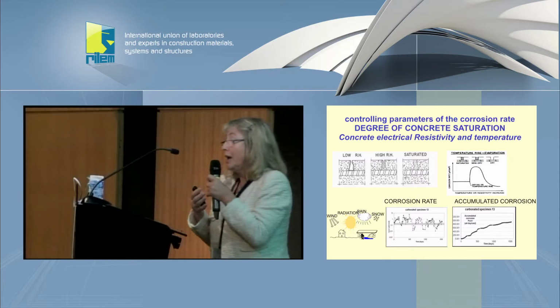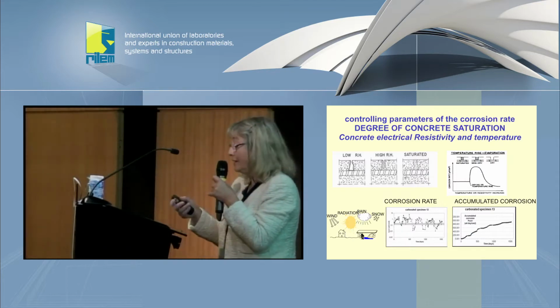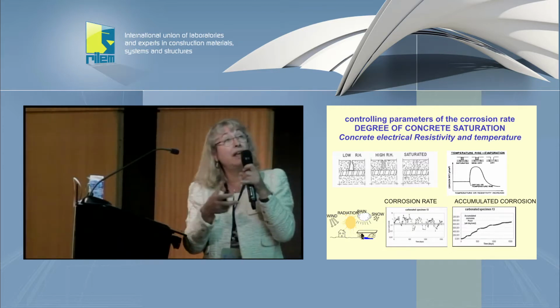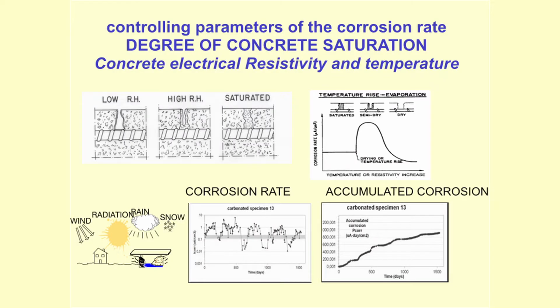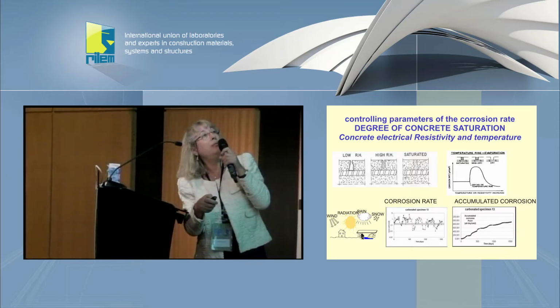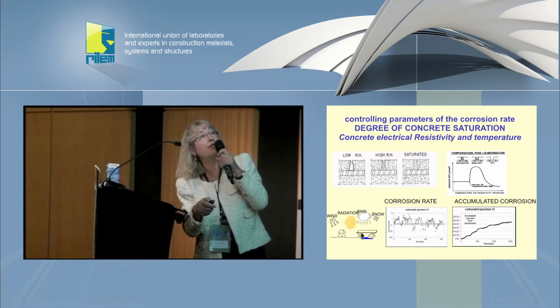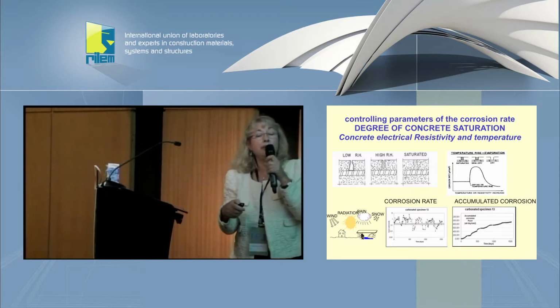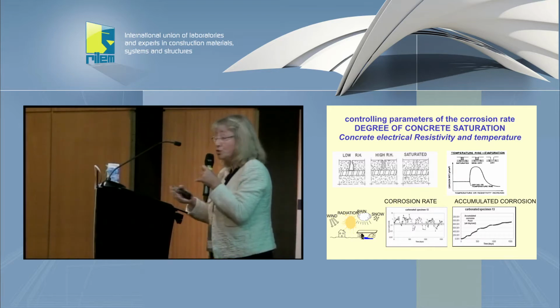Is that happening in reality? This can be predicted in some manner, not only saying that this is the simple model. Well, yes, the corrosion is dependent on the amount of liquid water in the concrete, that is, of the degree of saturation or the volumetric fraction of water. In that case, if we are able to measure the amount of water remaining in the concrete depending on the ambient, it will be possible to have the degree of saturation, and from the degree of saturation we can finally have the corrosion, as I will show.